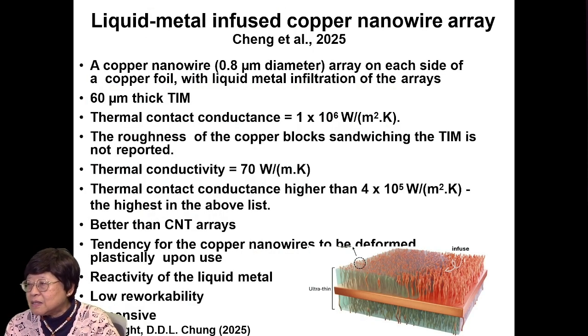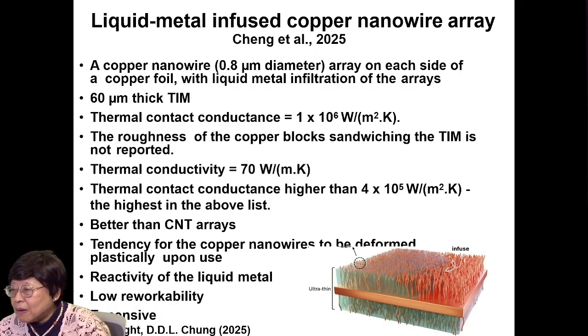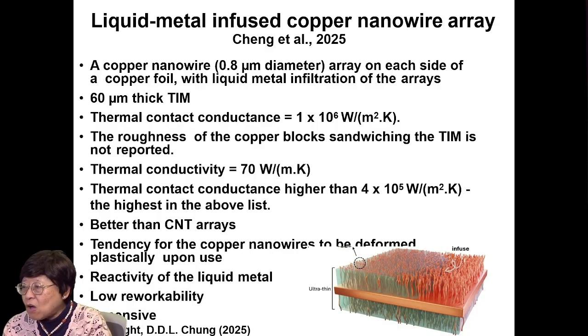However, not shown in this list is very new work reported by Cheng in 2025. It is a liquid metal infused copper nanowire array. It is a copper nanowire, 0.8 micron diameter array on each side of a copper foil, with the liquid metal infiltrated into the arrays. This TIM has thickness 60 microns. The thermal contact conductance reaches 1 times 10 to the 6 watts per meter square K, which is higher than that of the best in the list that I showed you.